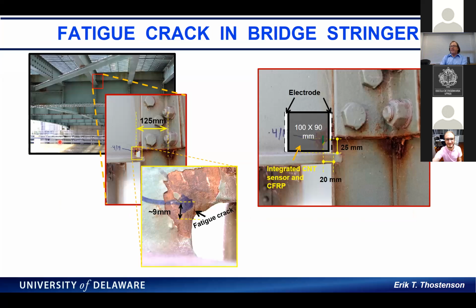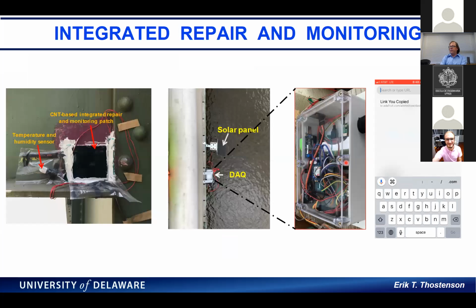This is the crack. You can see some corrosion, but you can also see the fatigue crack that initiated. And this was actually initiated at a previous repair. So we designed an integrated sensor, and we have two sensors on this bridge. We're also measuring temperature and humidity. This is all sent to us over the cellular network, and it's self-powered by a solar panel.